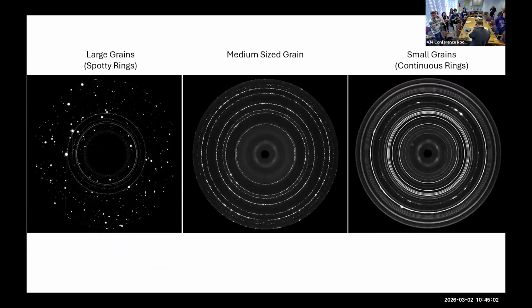But okay, so that means you need enough grains to fill up the whole circle. So if you look at the picture on the left, there's not a whole lot of grains within the beam path, because each grain will just produce a dot. And if you have enough of them that are randomly oriented, you'll fill up the whole circle. But this one doesn't really have that many. So you're mostly just seeing a bunch of dots. This one you have more, but you can still see the spaces.